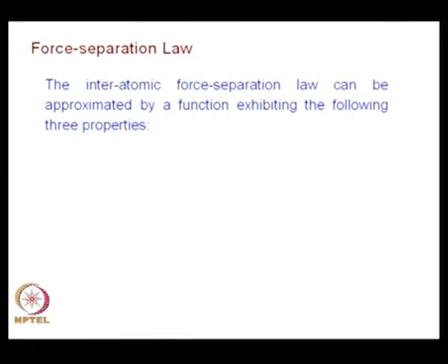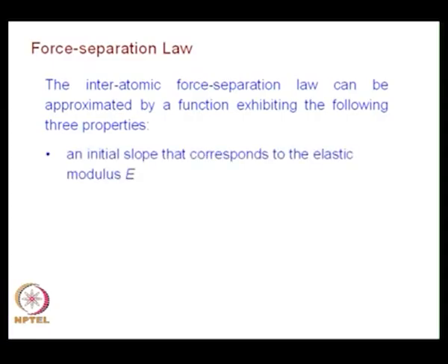Our interest is to see what kind of result people have got based on lattice property calculation. So, if I want to have the force separation law, I need to consider the law such that the initial slope corresponds to the elastic modulus E of the material, whatever the material that you are looking forward to.